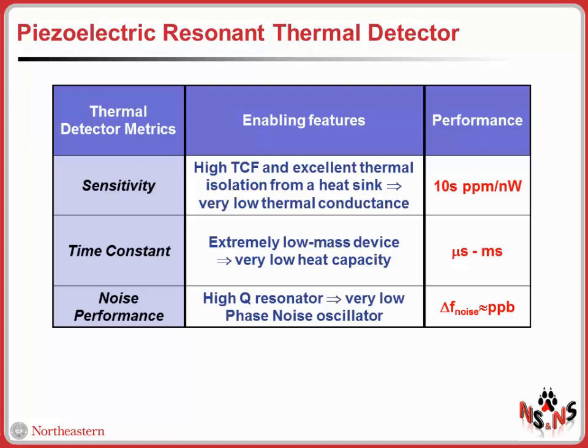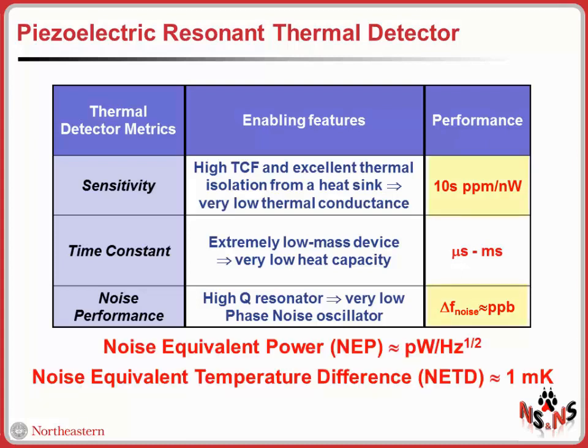But also very important is the noise performance of the device. These devices are based on high Q mechanical resonance. And in fact, using this kind of devices, it's possible to implement frequency sources that are characterized by a very low phase noise. So you see typically the noise-induced frequency fluctuations of this kind of devices in the order of parts per billion range. So really, by combining this noise performance with the very high sensitivity of the device, it's potentially possible to achieve a figure of merit for infrared sensors that is quite promising, quite interesting.